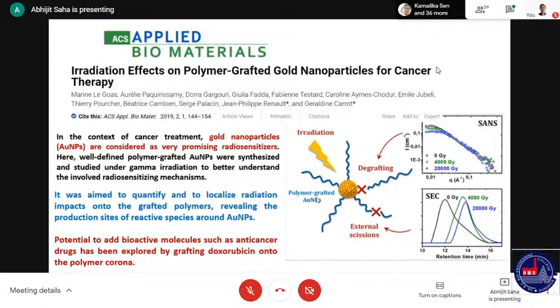So what are the sites from which degrafting has taken place? That gives you the idea of where the radiosensitization active sites are, what the active sites of the radiosensitizing materials are. You can get some idea about that. So it was aimed to quantify and to localize the radiation impacts on the grafted polymers, revealing the production sites of reactive species around the gold nanoparticles.